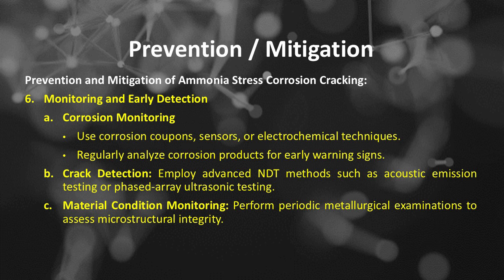Prevention and mitigation of ammonia stress corrosion cracking. Number 6 is monitoring and early detection, which includes: number A, corrosion monitoring. Use corrosion coupons, sensors, or electrochemical techniques. Regularly analyze corrosion products for early warning signs. Number B, crack detection. Employ advanced NDT methods such as acoustic emission testing or phased array ultrasonic testing. And number C, material condition monitoring. Perform periodic metallurgical examinations to assess microstructural integrity.